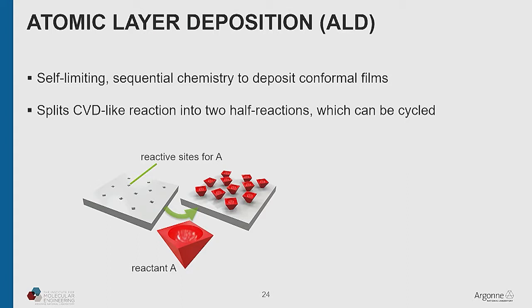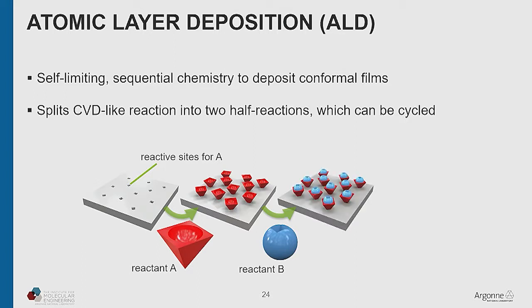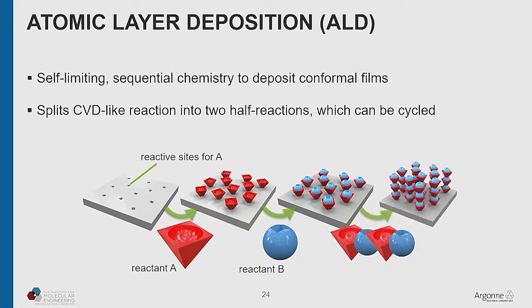Now, the cool thing about atomic layer deposition is that reactant A here, the first precursor, then provides a site for a second one, which will react with everywhere on the surface where there was reactant A. And that completes one cycle of atomic layer deposition. One cycle of A and B conformally coats a substrate with a single atomic layer, hence the name, of an inorganic material. And what's really cool here is that reactant B is designed to provide a site to react with A again. And so you can cycle A, B, A, B, A, B, and build up layers on top of one another, each one being self-limited, one atomic layer at a time, to conformally coat surfaces with great precision.